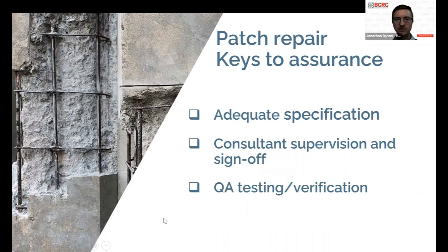So what are some of the keys to make sure that you get a good patch repair? Firstly, it's important to make sure that the specification for the patch repair is adequate and detailed enough. Probably in most cases, it's not really going to be enough just to tell them to follow the manufacturer's recommendations. It probably is worthwhile in most instances to have an experienced consultant develop a specification for the repair that's required. And then equally importantly, to make sure things are done as per the specification, it's important to have an experienced consultant supervise and sign off on the repairs.